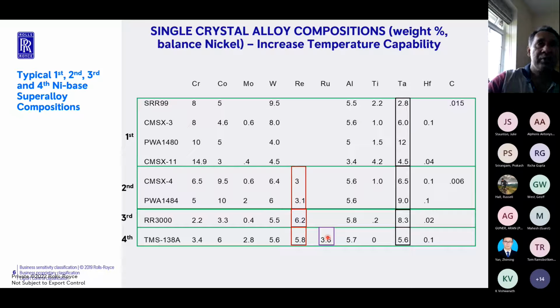So the tendency for you to form TCP type phases is diminished. So it's possible for you to slightly increase the amount of chromium and therefore not lose out on the oxidation compared to what you would have lost in a third generation alloy. And at the same time, the alloy also retains its strength. So whilst you can recover your stability, or in other words, make it less unstable, you do also get some increase in the amount of oxidation performance.